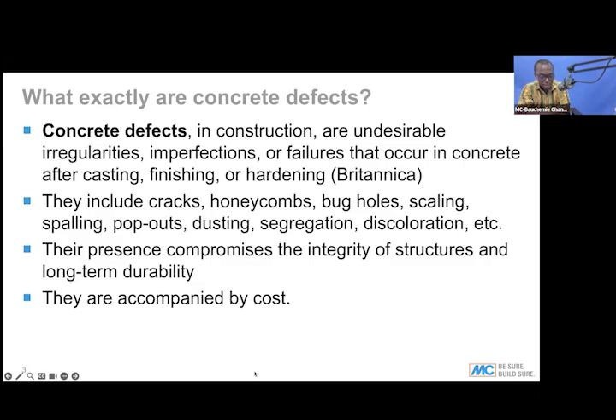Right. So as I mentioned, cracks, honeycombs, bug holes, scaling, spalling, pop-outs, dusting, segregation, discoloring are all defects that may happen to the concrete, but they all have degrees of impact on the concrete. For instance, if it's just discoloration, it might not be a structural issue, but when you end up having shrinkage cracks, plastic settlement cracks, then that becomes a structural issue because these cracks allow the ingress of external factors such as carbonation or chloride attacking the reinforcement, and that can cause damage to the structure. So these are defects that may happen.